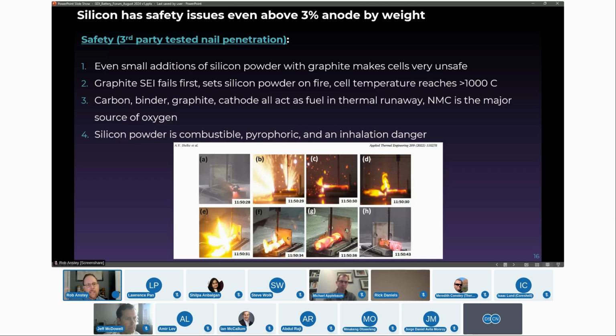With most of these nickel-based materials, you release a ton of heat and a lot of oxygen. And guess what? Silicon loves heat and oxygen, right? It wants to be SiOx. And if you make a nanowire, a nanostructure, a nanocarbon composite, what do you got? A ton of surface area. All of that wants to interact with the gas and the heat and the byproducts. Next thing you know, these things are going up to 1,000 degrees Celsius or higher.